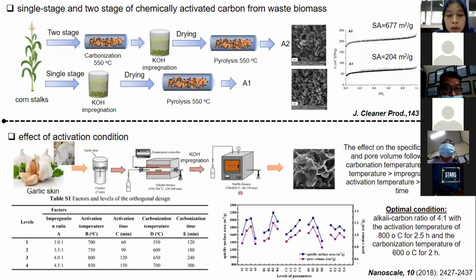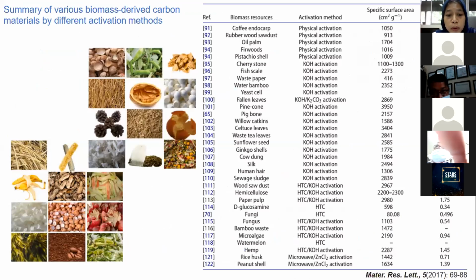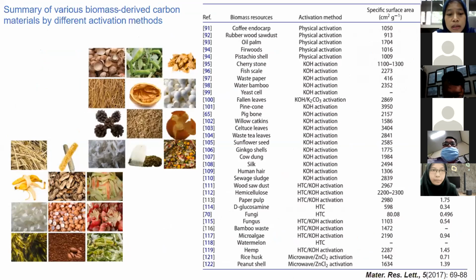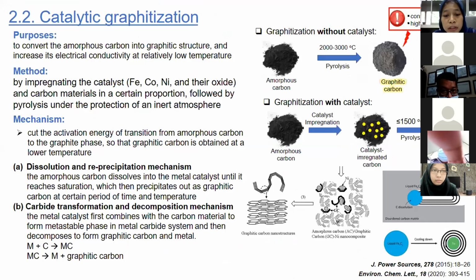Okay, this slide is just a summary of various biomass-derived carbon materials by different activation methods. Many biomass wastes were proved to be usable as activated carbon with high porosity and surface area using the activation process. And next is the catalytic graphitization method. During chemical activation, the porous structure of biomass can typically be developed, but the graphitic structure is ordinarily not perfect, causing relatively low electrical conductivity and limiting its application. So it is necessary to improve its graphitic structure to enhance the electrical conductivity.